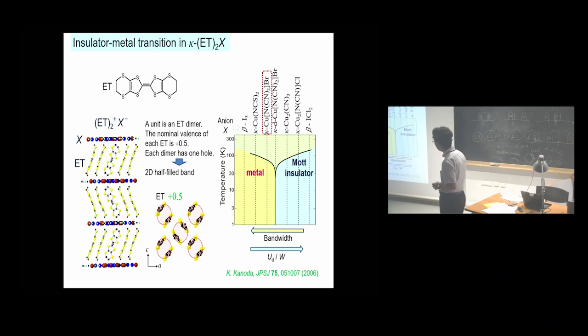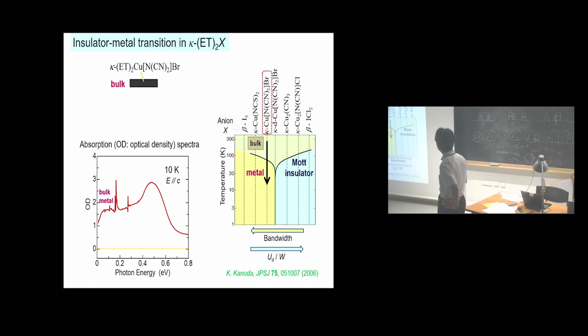This is a projection of the ET layer on this plane. A unit is an ET dimer. The nominal valence of each ET is plus 0.5, and each dimer has one hole. So, a 2D half-filled band is formed in this compound. This is a schematic phase diagram of the ET2X family. The horizontal axis is the effective bandwidth, which can be controlled by the choice of X. This is a metal-Mott insulator boundary. Here we focus on this compound with X equals Cu[N(CN)2]Br.